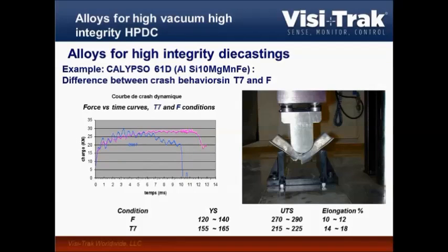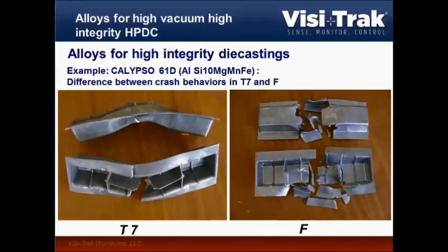Static mechanical properties taken in a low-speed tensile test, as mentioned before, can be quite problematic. Here, these were tests conducted in Europe by Pechiney, actually more than 10 years ago, and they said, well, let's compare it in real crush tests or crash tests, and they had alloys with relatively similar static mechanical properties. But then if you crash them and you compare T7, as mentioned before, solution heat treated and overaged, and F condition, just as cast, you will see the result is the heat-treated parts survived the crash test.